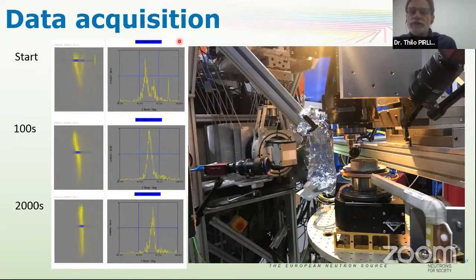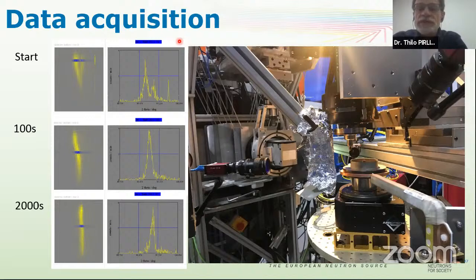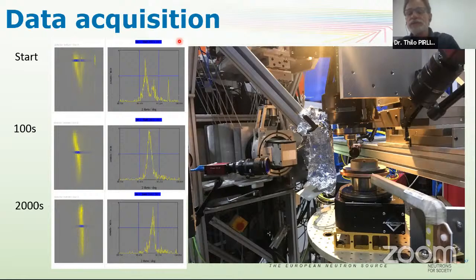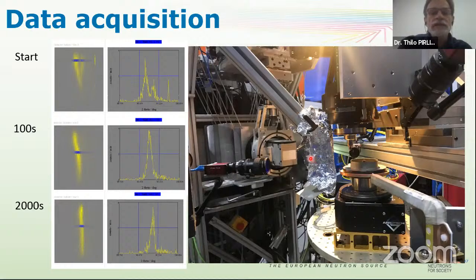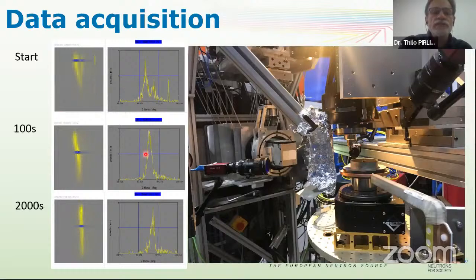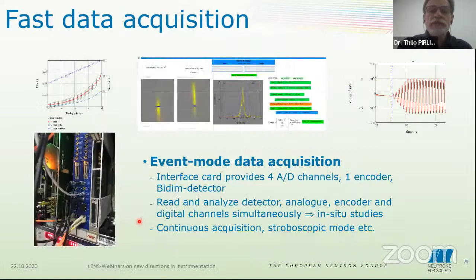How to further improve an instrument: we now have the highest flux possible, position-sensitive detectors, and good beam optics. We want to measure fast, and if we can do some imaging, that would be perfect for in-situ experiments. One example is in-situ additive manufacturing: we were printing a nickel piece using additive manufacturing, and we could image the vertical line of this build while it was building, obtaining diffraction peaks from different times at different heights in the sample. This is possible due to event mode data acquisition.